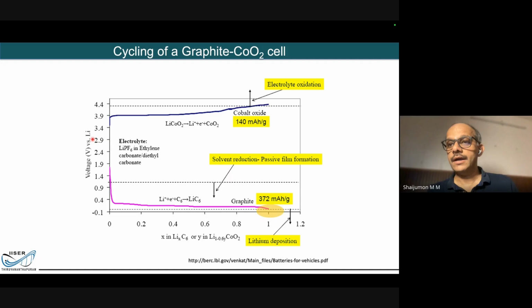And just to give you the idea of what is the source of this voltage that we talk about, I don't know how many of you know that the voltage of a lithium-ion battery is about 3.6 to 3.7 volt, right? Compared to what we know, about 1.5 volt for other batteries, right? So what's the source of this voltage? It's very simple. It is the difference between these two operating potentials at any point of time, right? So you have around 3.9 to 4, and you have around 0.3 to 0.4, which gives you an average potential of about 3.6, 3.7 volt, right?